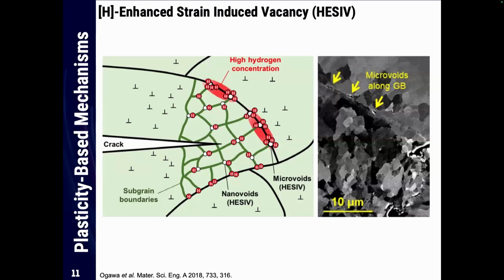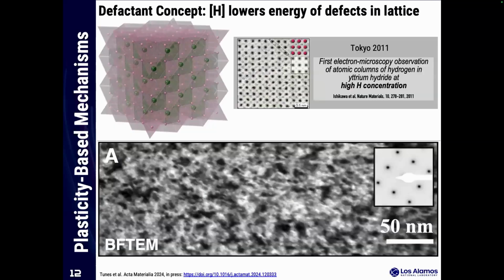This is one of the seminal papers in the area of hydrogen embrittlement theory. I highly recommend you guys looking into it. It's actually when you strain the material, you can produce defects, atomic defects like vacancies. They can agglomerate, interact with hydrogen, and nucleate microvoids where the crack propagation happens. There is also the defactant concept, and I have some new results to present on here.